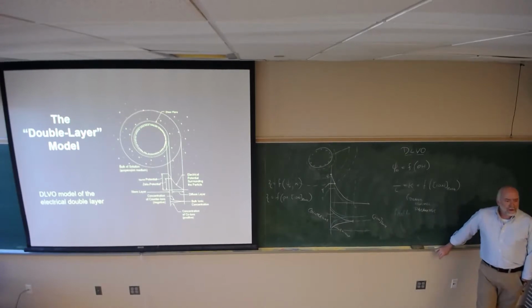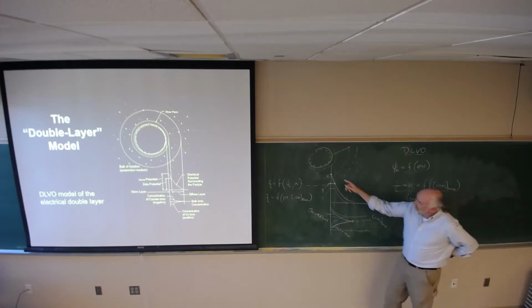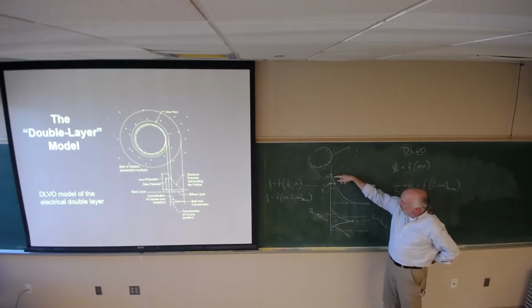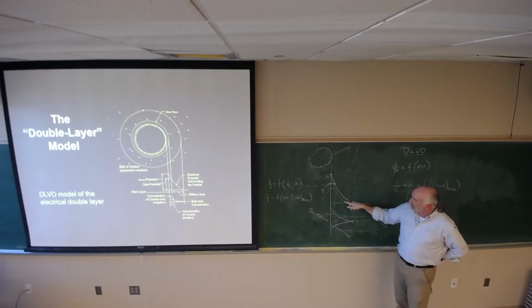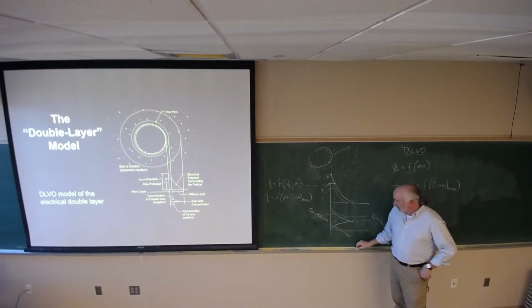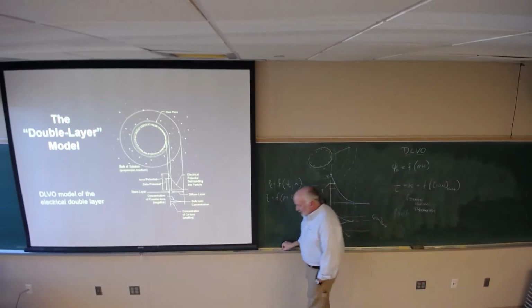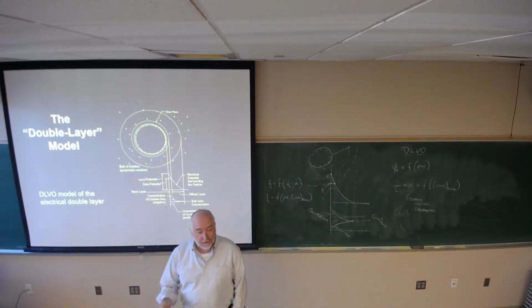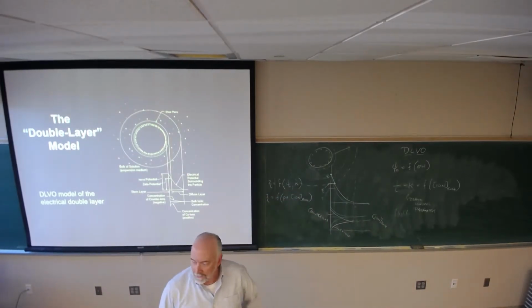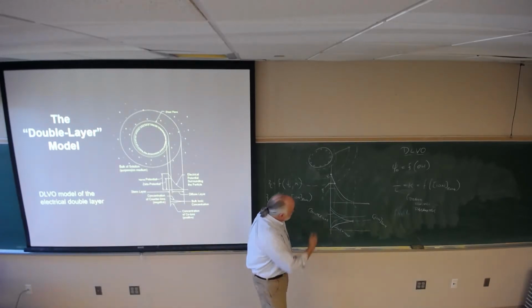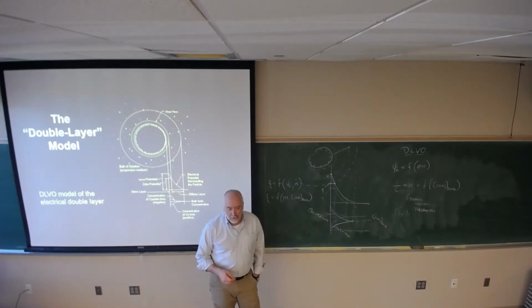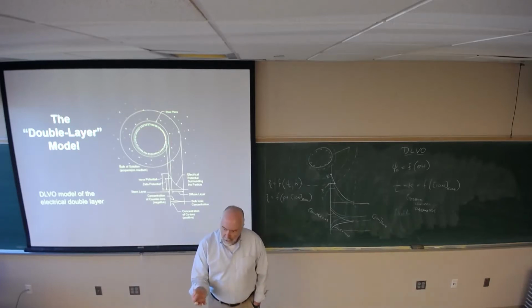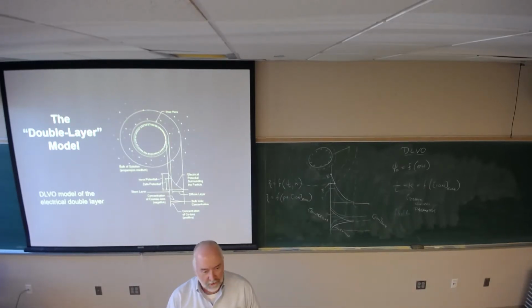So, I increase the bulk ionic concentration, and that causes then compression of the double layer. It gets smaller. That means I'm able to decay the charge away from the particle surface down to 0 in a shorter distance. That means my zeta potential decreases. What happens if I, say, change the pH? Okay, so I have this situation. Let's say I stay with condition blue. Okay, so I have my increased bulk ionic concentration, and I'm going to change the pH.